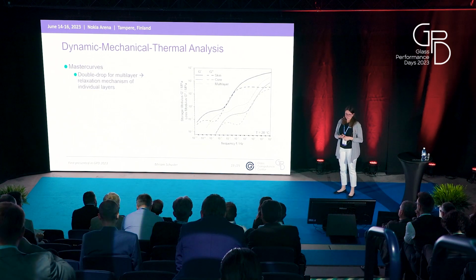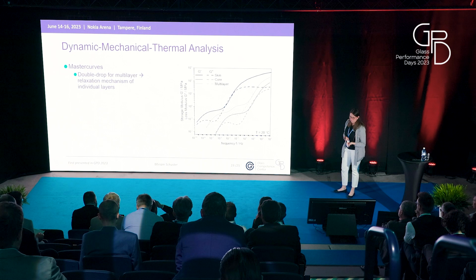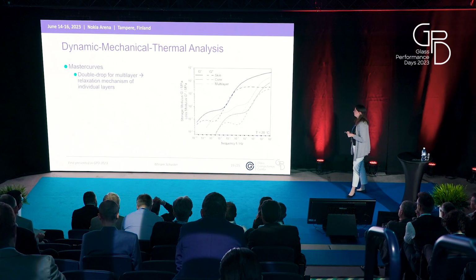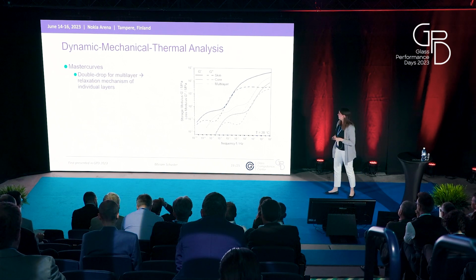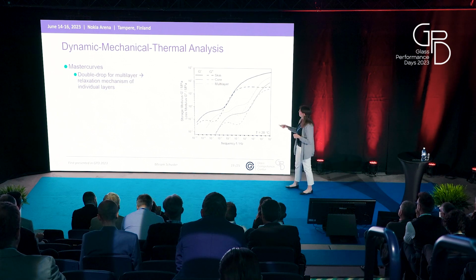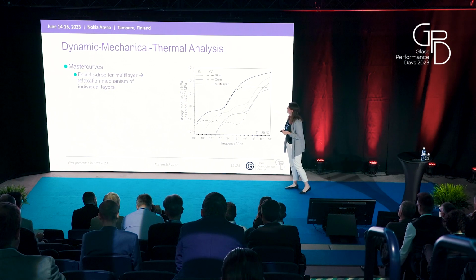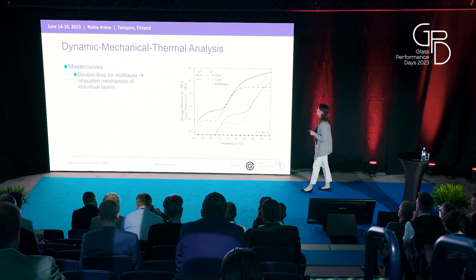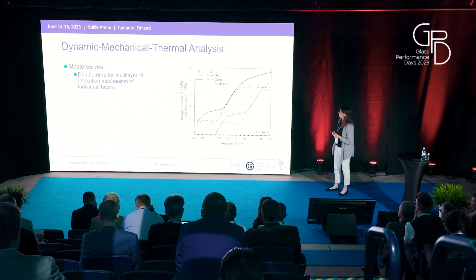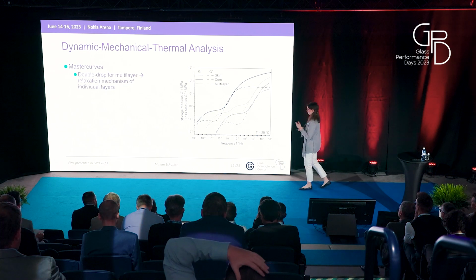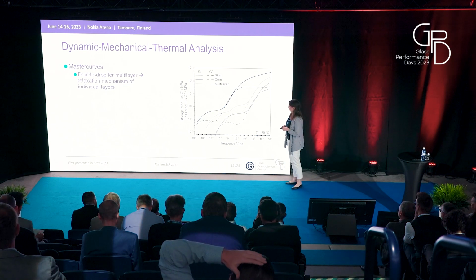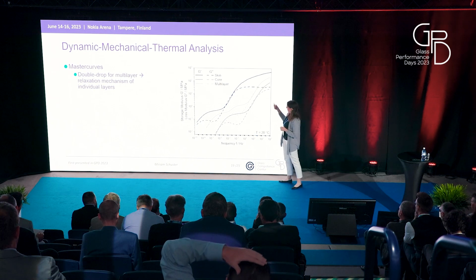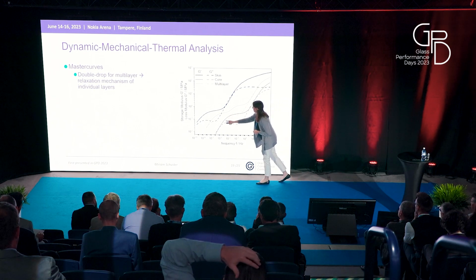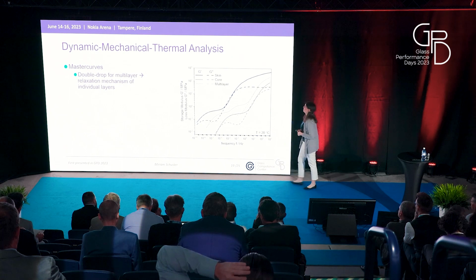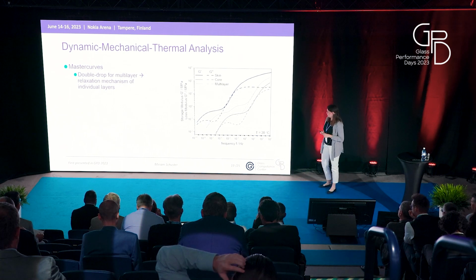For each of those tests, so the multilayer and the individual layers, we generated master curves. They are depicted here in the frequency range. So we have in continuous line the storage modulus, and in dashed lines the loss modulus curves. In all 3 cases, it was possible to create master curves by purely horizontal shifting. And what is interesting for the multilayer, we see here a double dip in the storage, but also in the loss modulus curve.